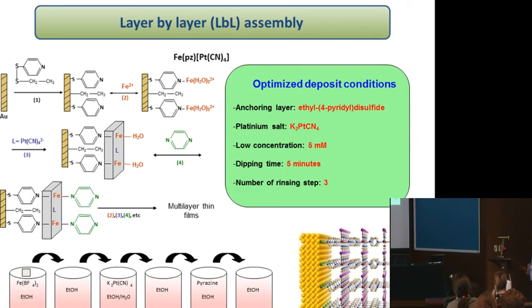Okay, you know a little bit this slide. So I just want to go into details concerning the synthesis. As Ine said, we can use the mercaptopyridine, but we have improved these anchoring molecules. In this case, we use this disulfide, and this branch is used in order to separate the pyridine function. And this is more in agreement with the three-dimensional structure of the material you use. Okay? So this is an improvement of this kind of deposition. So you start from a gold substrate, you functionalize, and then you use layer-by-layer techniques. This means first you attach iron, then you attach the platinate bricks here, and then the pyrazine, and you can repeat this kind of sequence to increase the thickness of the film you want to obtain.